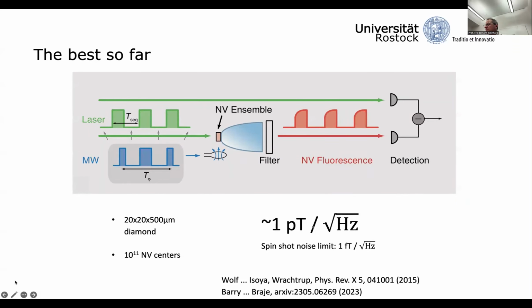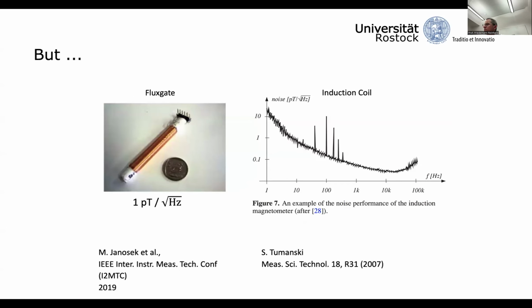And with that, they routinely reach a picotesla per root hertz now, but this is still orders of magnitude short of the theory limit that in principle should be achievable. Also, if we compare that to the market of magnetic field sensors, a picotesla per root hertz actually is not that impressive by itself. For example, flux gates can also reach that. Induction coils can also reach that. They can even go slightly below a picotesla.